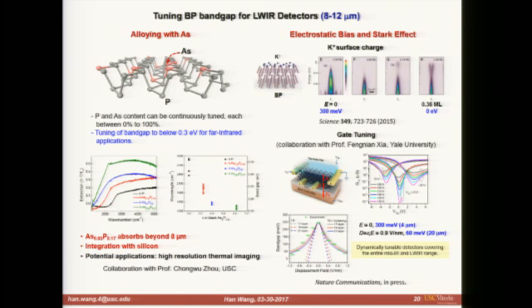One is alloying black phosphorus with arsenic, also a group 5 element. You start from black phosphorus and replace phosphorus atoms with arsenic atoms. The more arsenic you put in, the lower the band gap goes. In our previous characterization, with 83% arsenic content, the band gap goes to around 0.15 electron volts, corresponding to around 8 micron wavelength, and you can go even beyond that.